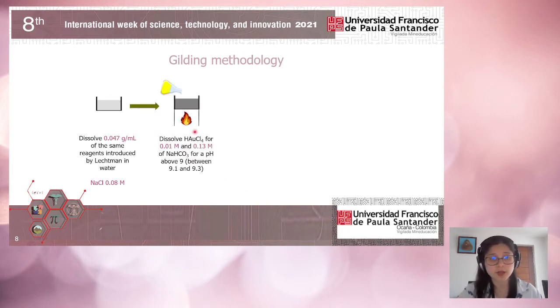Then we dissolved a gold precursor that was also described by Lechtman, and it's important to notice that we use less molarity, less concentration of this gold precursor, 0.01 molarity. Then we add sodium bicarbonate, 0.13 molarity, to give us a pH slightly above 9, between 9.1 and 9.3, depending on the temperature at which the pH measurement was taken.